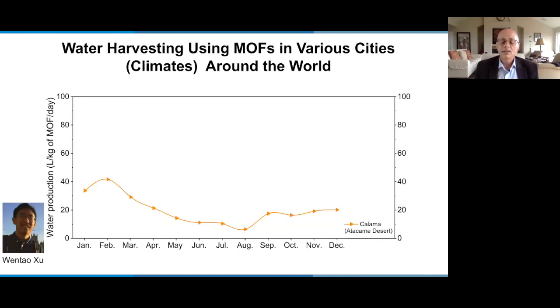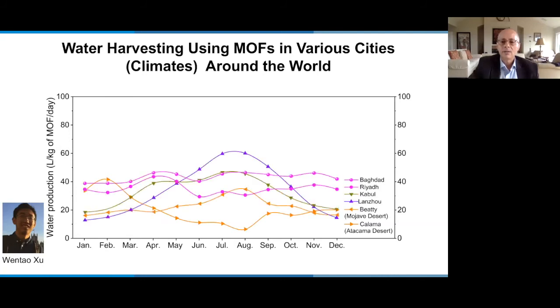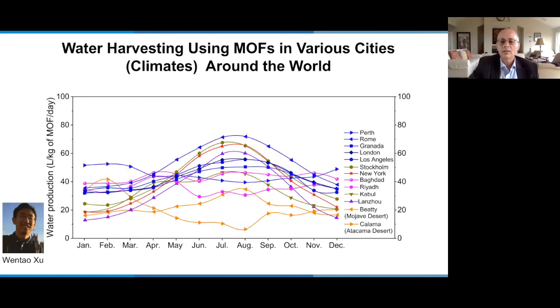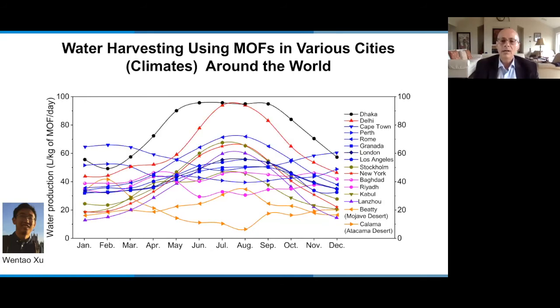The MOF, the amazing thing about the MOF, because it works at very low humidity, like 7% relative humidity, it will work in every part of the world. Just the question is how much water you will get based on which area of the world you are. So even in the driest deserts in the world, the worst you get is about 5 liters per kilo per day. But in general, in most of the desert regions of the world, you're getting pretty high amounts, 40 liters, 50 liters, 60 liters per day per kilogram of MOF.